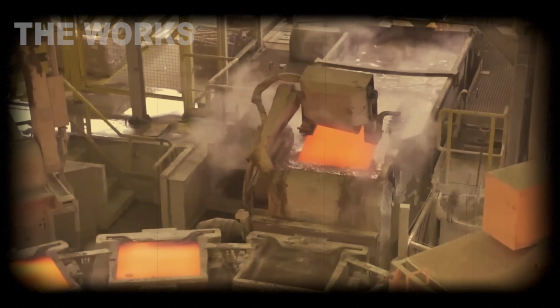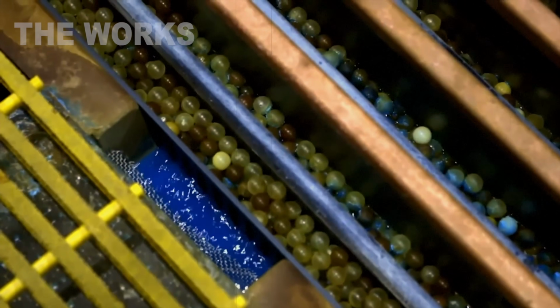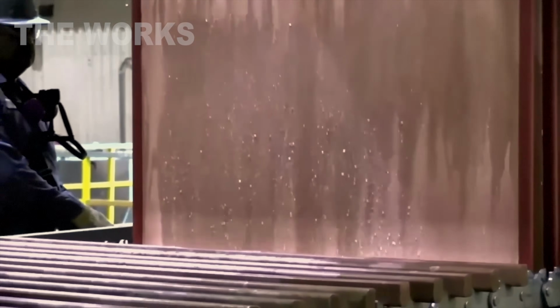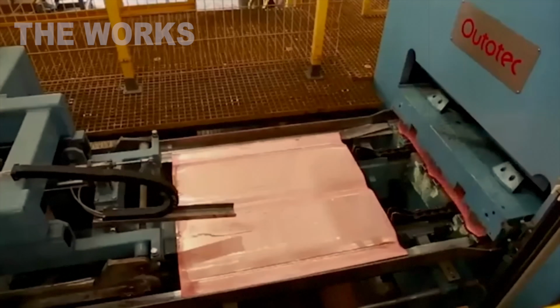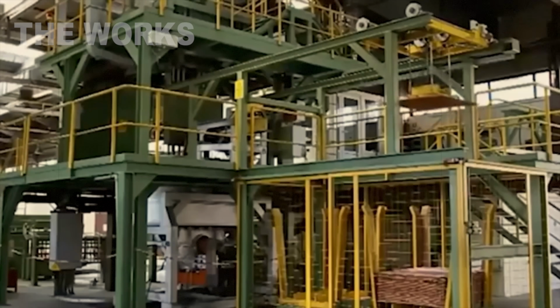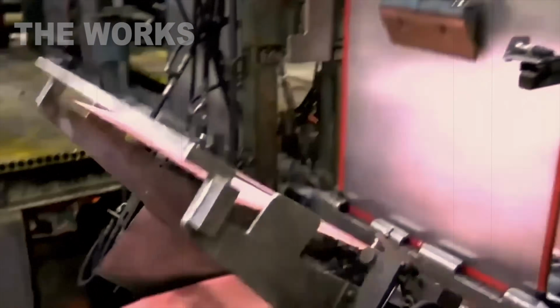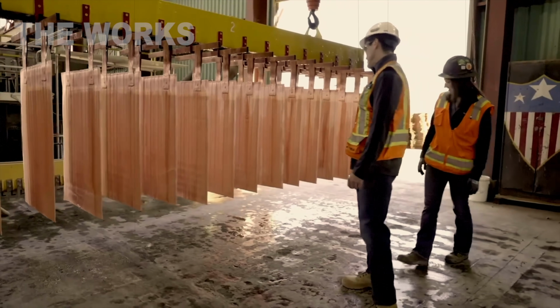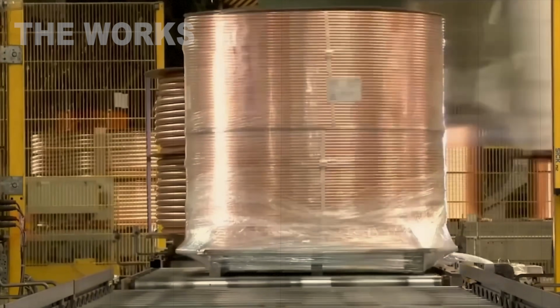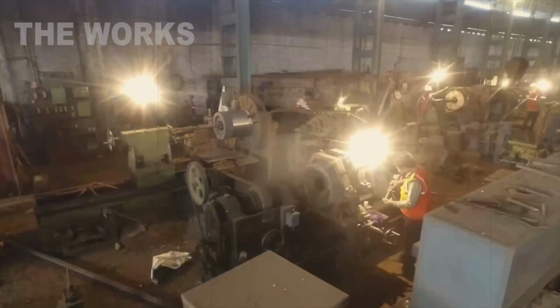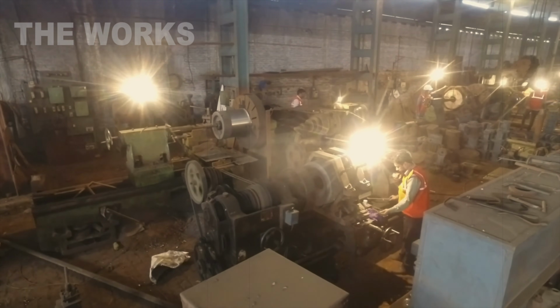Blister copper is cast into anodes 2 inches thick. They're submerged in tanks filled with copper sulfate solution. A current of 2 volts runs through. Copper dissolves off the anodes and deposits onto cathodes. After 3 weeks, the cathodes are coated with a layer of pure copper 4 inches thick. Purity, 99.99%. This is market-grade copper, ready to become wire.